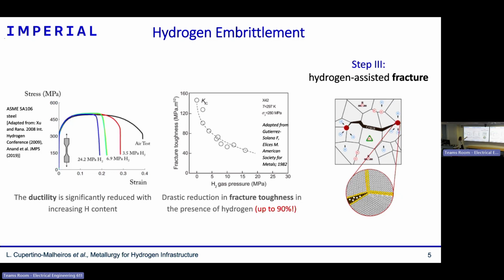So what you can see here is that testing it in air, you get this type of elongation, which is related to the resistance to fracture. But by doing the same test with the same material with increasing pressures of hydrogen, you get a dramatic decrease of the elongation that the material can withstand. So here, half of the elongation. So it's even more clear when you plot here, you do fracture resistance tests.